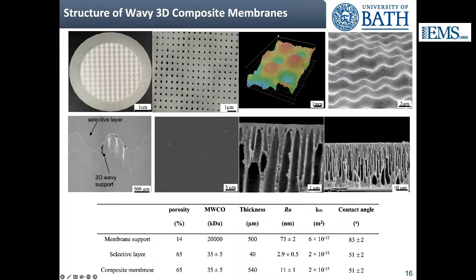If you look at the cross section on the bottom left, you can see very clearly that you have the brighter area, which is the selective layer, and then the underlying slightly less bright PES support. And at the right, 3D printed support, excuse me. On the right, you can see a cross section of the PES support with the classical structure you obtain from phase inversion.